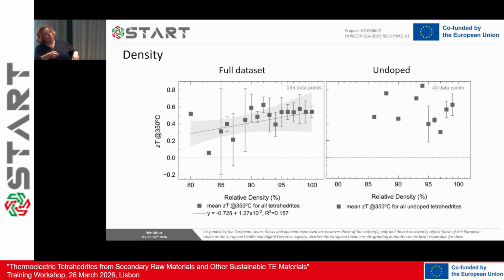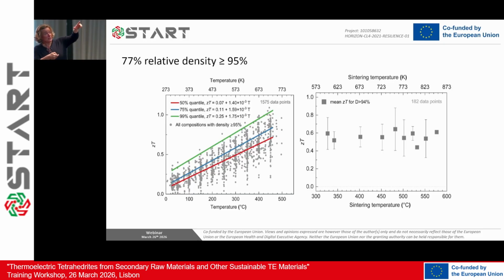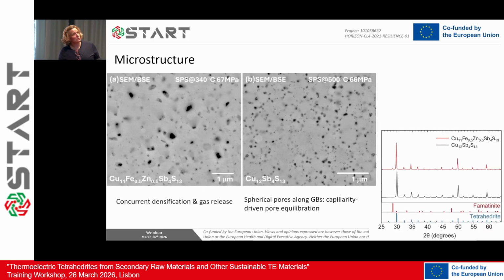You see that here is very messy, but here it tends to be more uniform. So it's good that samples considered for any benchmarking or study should have densities above 95. What we found is that 77% of reports in the literature have relative densities above 95%. Then when we plot it, we don't see much difference. We see very similar scattering, a little bit less, but it's not really affecting the result.